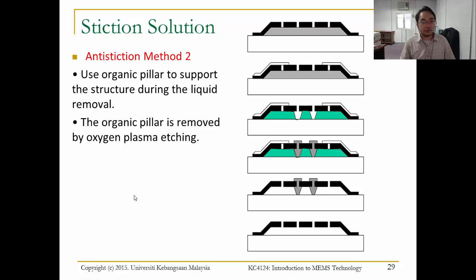Anti-stiction method number two is by using organic pillars to support the structure during the liquid removal process. Looking at the figure here, if for example we have a structure with a hollow body, when we want to remove the sacrificial layer in the hollow, we can plug in some pillars. The pillars here are to support the suspended dome during the drying process. Otherwise, the dome will be bent and stick to the substrate like this.